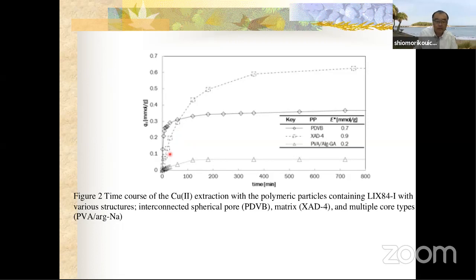The matrix type has a slow extraction rate. This slow extraction is quite a common phenomenon, because in the matrix type, the extractant is placed in quite small pores. The small pores of the particle were filled by extractant solution, and the small pores inhibit diffusion of the extractant and extraction complex in the organic phase. This hindrance of diffusion causes the slow extraction rate.